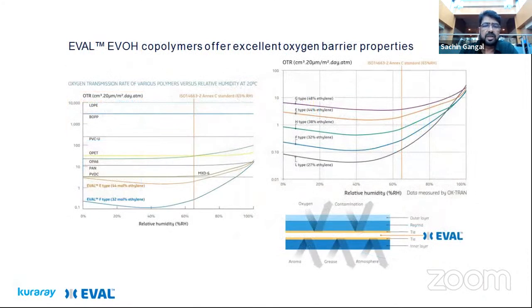We have several EVOH grades, which we classify on the basis of ethylene content. Thumb rule is lower the ethylene content, better the barrier, but we also have to think of processability. So certain grades are suitable for certain applications, like at the top of the slide, if you look at the G grade, which is 48% ethylene content grade, we recommend that for BOPP applications. Next slide, please.